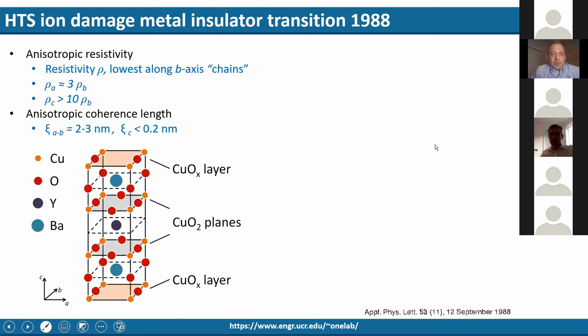I work on Josephson junctions in high-TC materials, and that's mainly what my talk's going to be about. High-TC materials were discovered in the late 1980s. And these are much different than conventional superconductors in that they're ceramics, and they don't have as many charge carriers, and they have these complex crystal structures. YBCO crystallizes in an orthorhombic structure, and it's different in every direction. And so that gives you the resistivity and electrical properties that are different in every direction, as well as a coherence length.